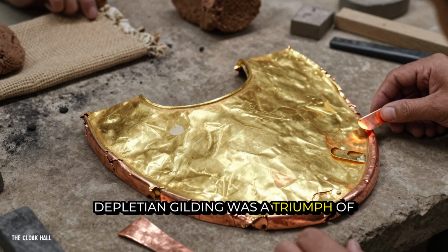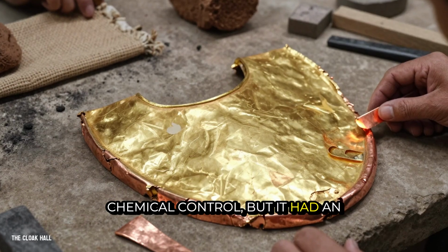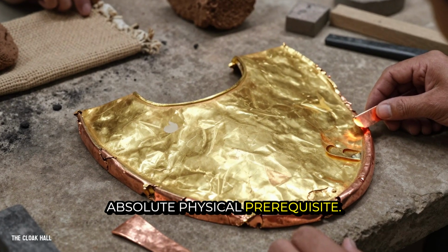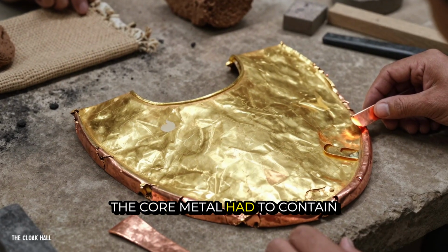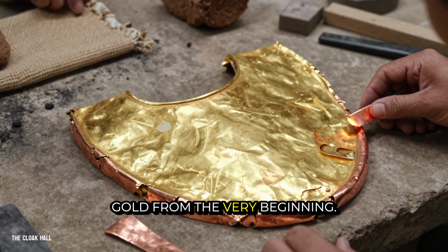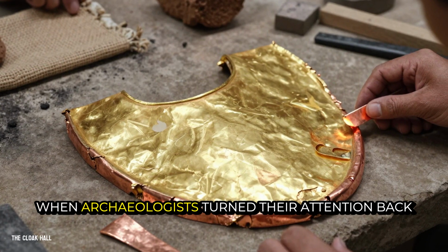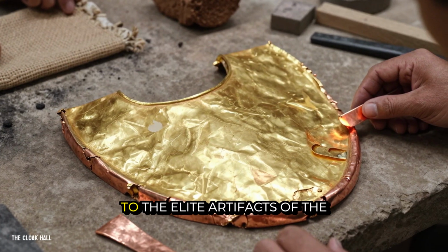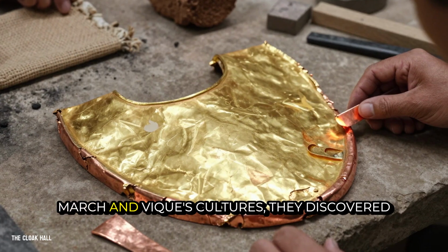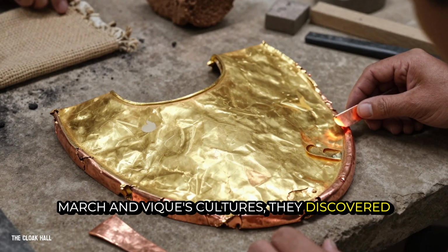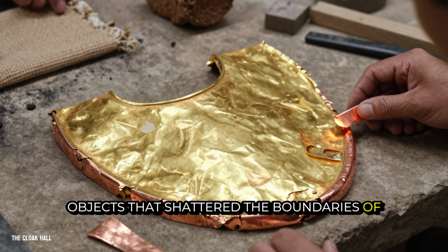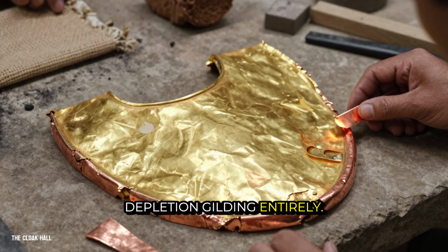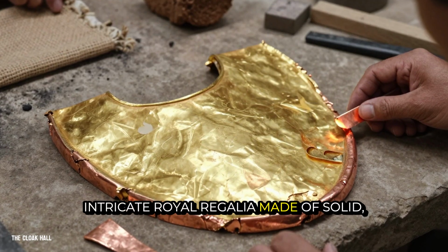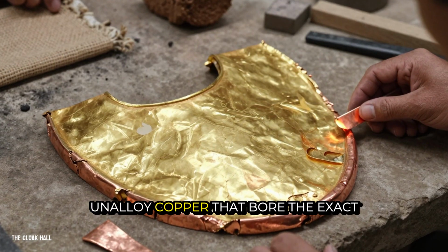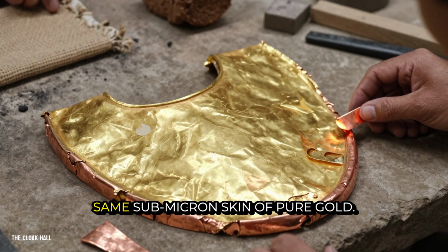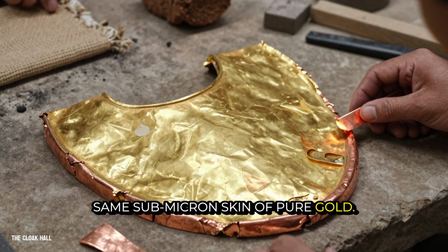Depletion gilding was a triumph of chemical control, but it had an absolute physical prerequisite. The core metal had to contain gold from the very beginning. When archaeometallurgists turned their attention back to the elite artifacts of the Moche and Vicús cultures, they discovered objects that shattered the boundaries of depletion gilding entirely: intricate royal regalia made of solid, unalloyed copper that bore the exact same sub-micron skin of pure gold.